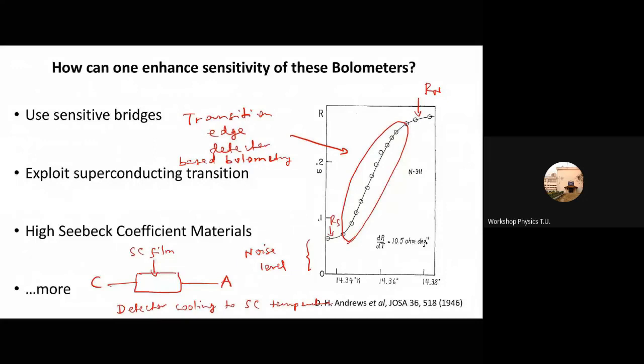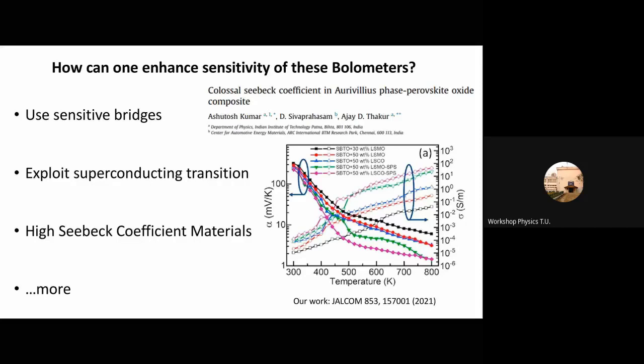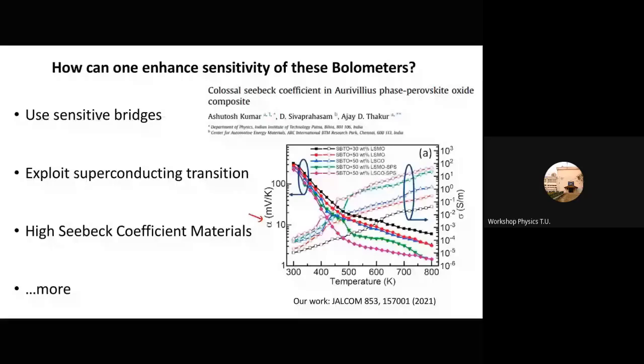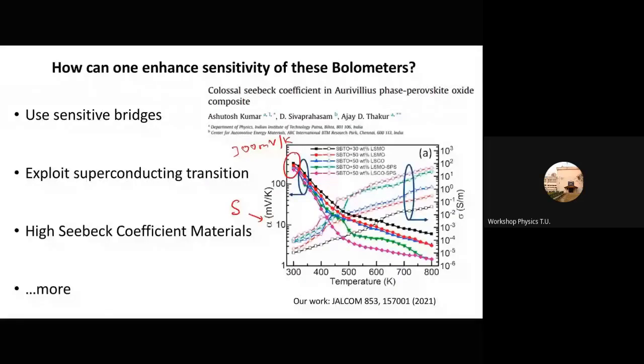There is some work which came out from our group recently that is based on this colossal Seebeck coefficient in Aurivillius phase-perovskite oxide composite. So here you can see that this alpha, or more commonly the Seebeck coefficient S, is about 300 millivolt per Kelvin at room temperature, and this was achieved via a special choice of materials, and I would be coming to that discussion in a while.